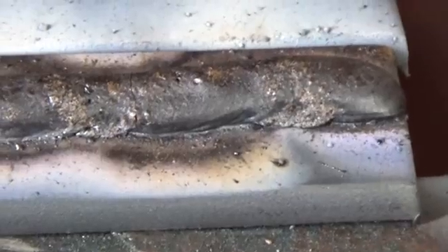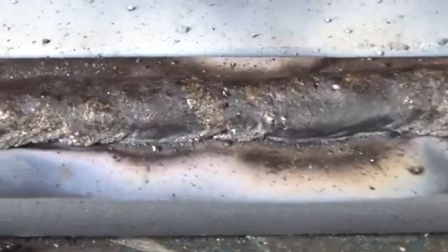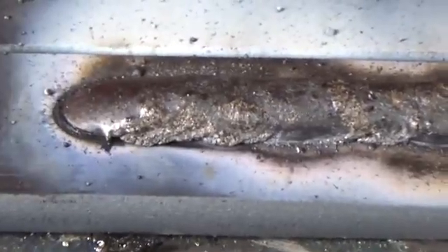So, the first weld: rutile electrode, negative, welding current 65 amperes. It can be clearly seen that the puddle is quite cold. Metal spreads poorly on the details. The welding process is too slow. The arc burns dimly. It is unstable, i.e. it walks from side to side, so it affects the seam. Let's clean the weld and look at that.